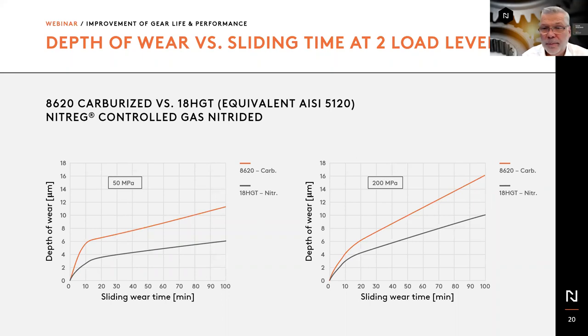shown here with a pin-on-disc test under two different loads, and you see equivalent steels, the 18 HGT is a European version of 5120, somewhat similar to 8620 in carburized material. So you can see that the wear rate is much higher on carburized material. This is because the tribology of carburized surfaces is poor. Hardness may be there, but it's not a type of surface that will produce a better resistance to sliding wear or to galling.